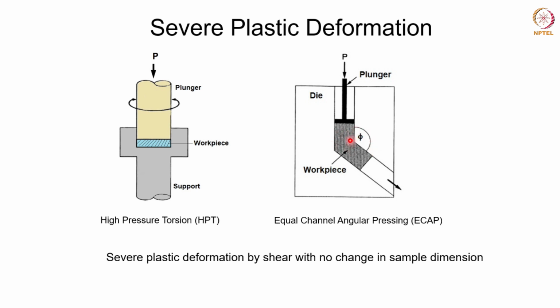So this is the workpiece which is inserted into the die, and now it is pressed with the help of a plunger like this. As you apply a load through this plunger, this material will be deformed inside this die, and then through this angle it will come out from the other side without any change in the dimensions, as I said before. Although a large amount of strain and deformation is introduced into the material through this plunger and the load applied, there will be no change in the dimension of the workpiece.